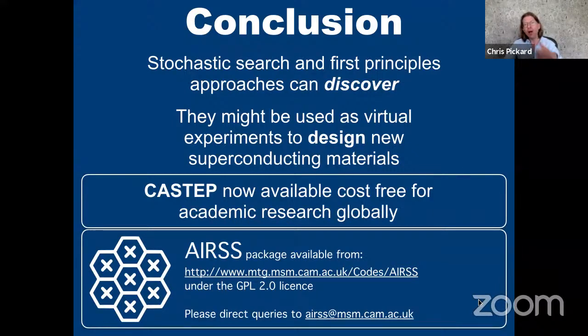In terms of using a lower level of theory for the TC to speed things up, actually, that doesn't help. The slow thing is calculating the electron-phonon coupling constants, so calculating the phonons and converging the integrals over the Fermi surface. It's really the fact that you've got these very complicated Fermi surfaces and you're having to integrate these quite delicate functions. That's what takes all this time. Allen-Dynes, Eliashberg, McMillan, that's just sort of post-processing. So our recommendation probably is just use Eliashberg because it works in the wider range and is fast compared to having to do all the phonon calculations.